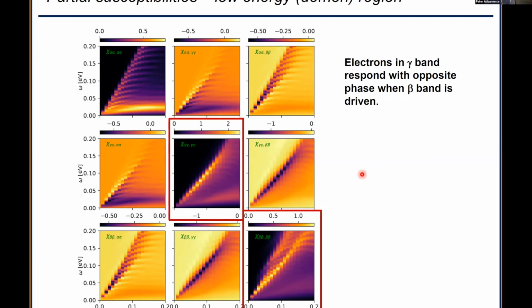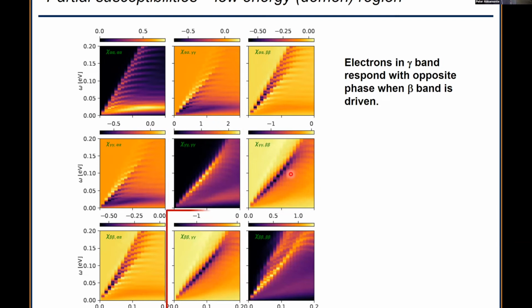What you can show is that for the in phase, if you drive the gamma band and look at the gamma response, it has a positive sign, but if you look at what happens to the beta band when you drive the gamma band, it has the opposite sign. So what it means is that a demon basically is a thing where electrons in one band oscillate out of phase with electrons in another band. So if I drive one of them, I can look at the sign of the response of the other one and ascertain whether it's in phase or out of phase.